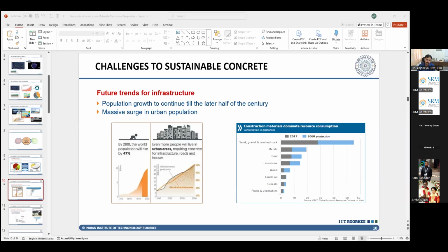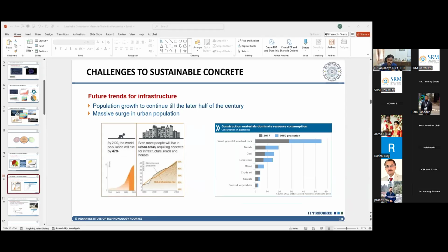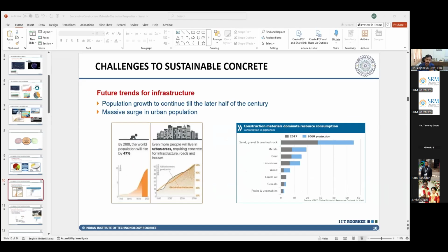Now, where does cement come into this? If you look at the global cement CO2-related emissions, they have increased according to the production of cement. Now, why is that? For every ton of cement that we produce, we have components coming from limestone decomposition, the fuel that is required to produce cement, and the associated ancillary activities like grinding and quarry. The problem is, even if you do away with all the fossil fuels and start making cement from completely green energy, you would still have about 50% of the emissions coming from limestone. This accounts for about 500 kg of CO2 for every ton of cement that is produced.